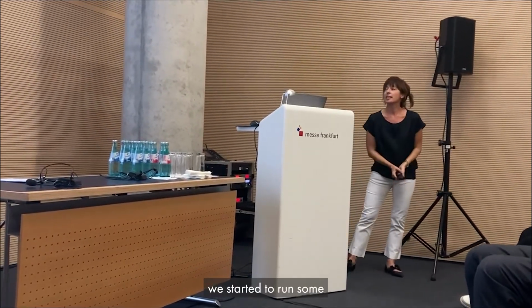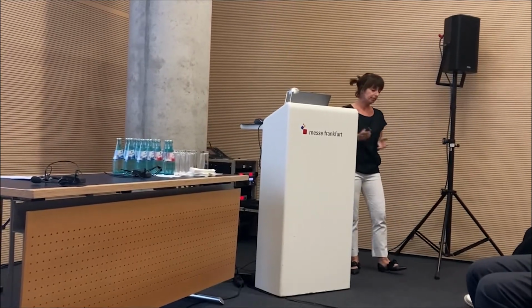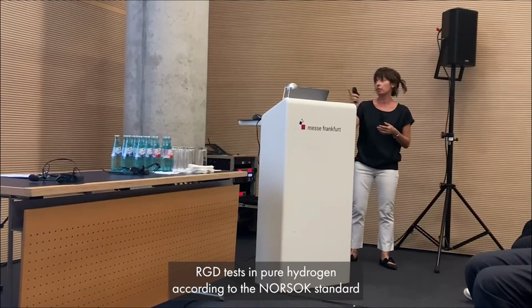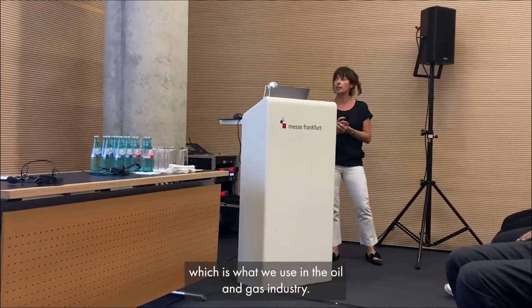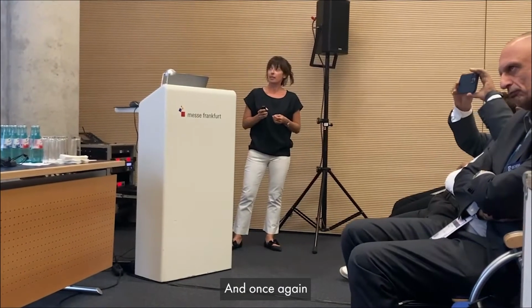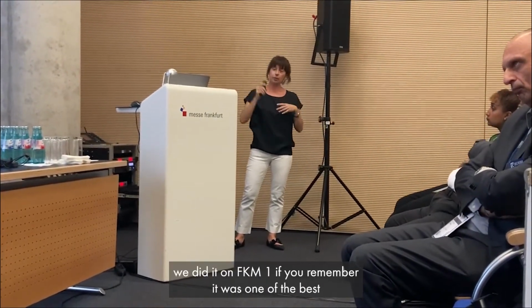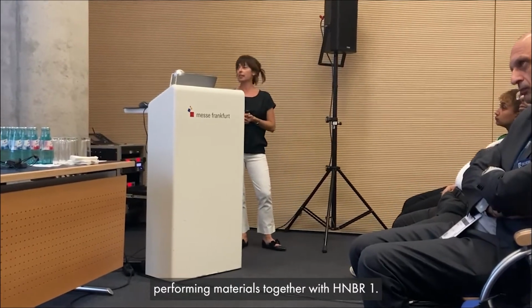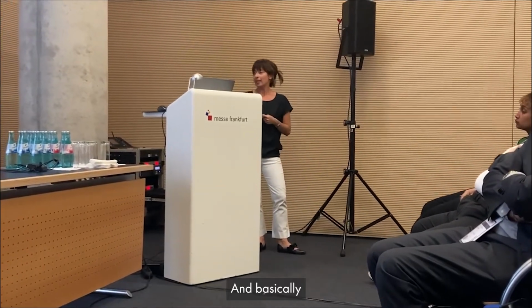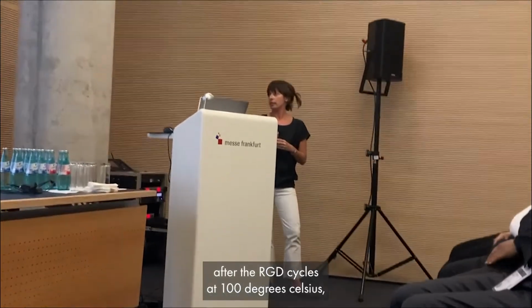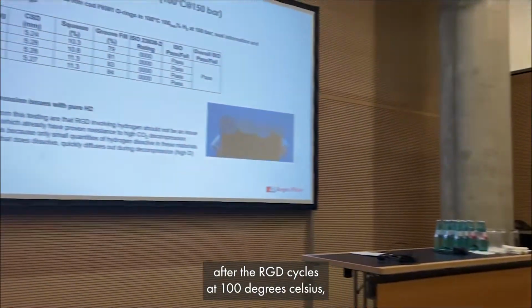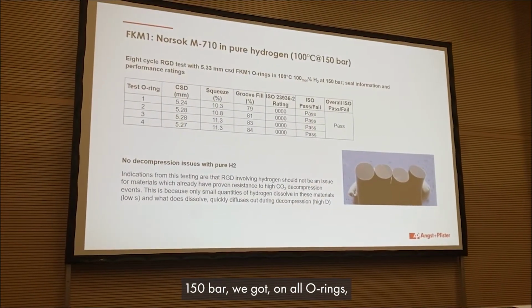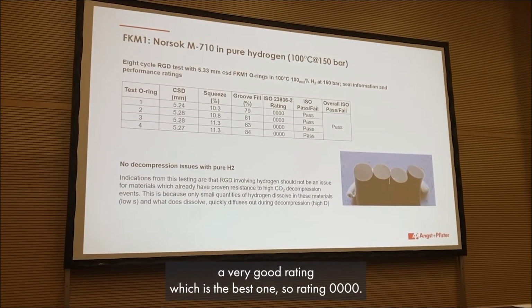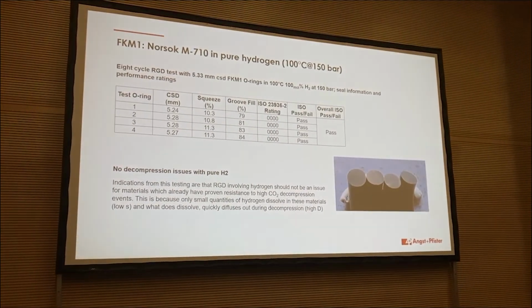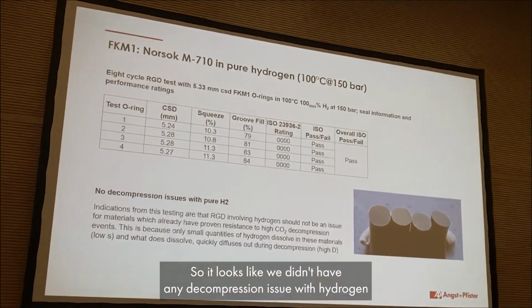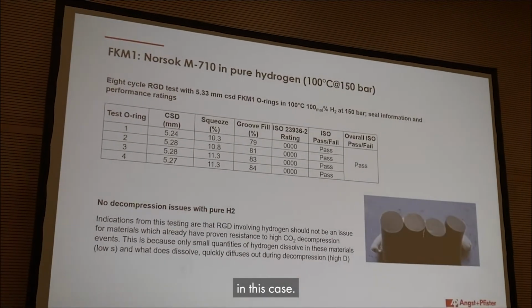We did start running some rapid gas decompression, pure hydrogen, according to the NORSOK standard, which is widely used in the oil and gas industry. And once again, we did it on FKM1. If you remember, it was one of the best performing materials, together with HNBR1. And basically, after the rapid gas decompression cycles at 100 degrees C, 150 bar, we got on all O-rings a very good rating, which is the best one, so 0000. So it looks like we didn't have any decompression issue with hydrogen in this case.